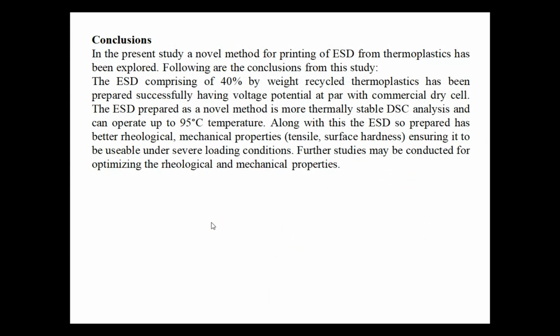So if I have a covering shell of ABS in which these chemicals or salts have been reinforced as a secondary way of recycling, we were able to use it at excessively high temperature as well as at low temperature, right? And there was another important thing, that we were able to consume 40% of the polymers, which is basically recycling. So this is another way of waste management through recycling, following the additive manufacturing route. Additive manufacturing is putting the material layer by layer. I am printing the disc layer by layer.